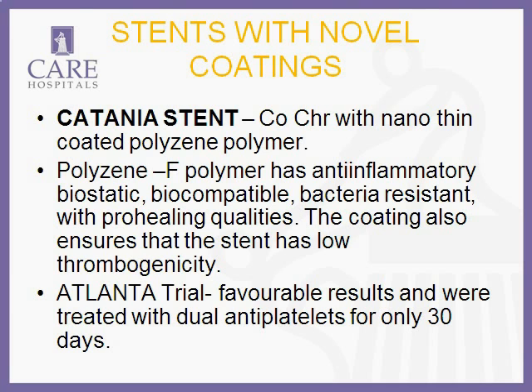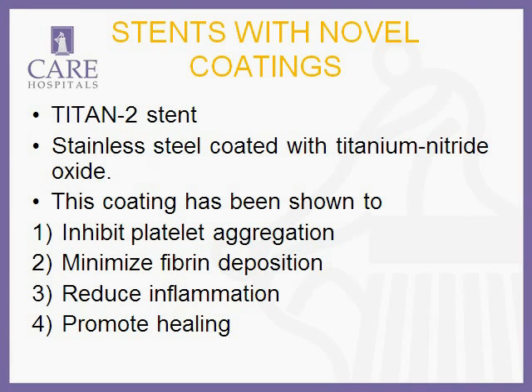Now, coming to the stents with novel coatings, it's the Catania stent which is being developed, which is a cobalt chromium stent with a nano-thin coated Polyzene polymer. This Polyzene polymer is anti-inflammatory, biostatic, bacteria-resistant, and biocompatible with pro-healing qualities, and the coating also has low thrombogenicity. Now, the ATLANTA trial has shown that these patients used dual antiplatelets for only 30 days, and there was no stent thrombosis as such.